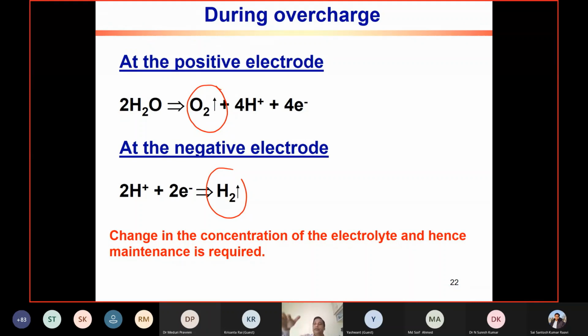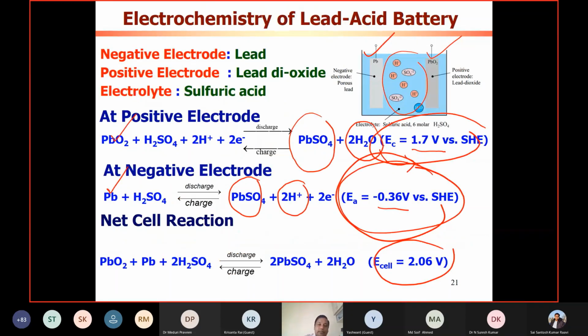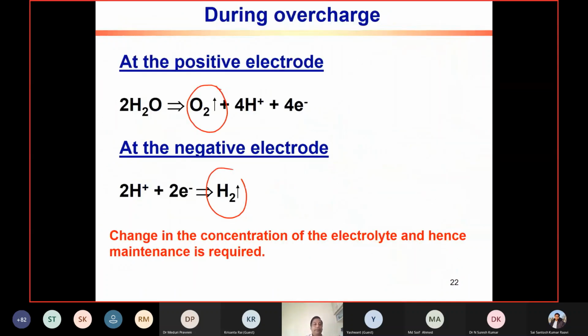If the concentration changes, suppose the level of water reduces to half, that means the concentration significantly changes. If it is very high concentration, then there will be a lot of sulfate formation. As you see here, once lead sulfate is formed at the positive and negative electrode, it stops the charge. The charges cannot enter into the bulk of the electrodes actually. That stops the electrochemical reaction. So, how to reduce lead sulfate formation? That's what we'll talk about today.